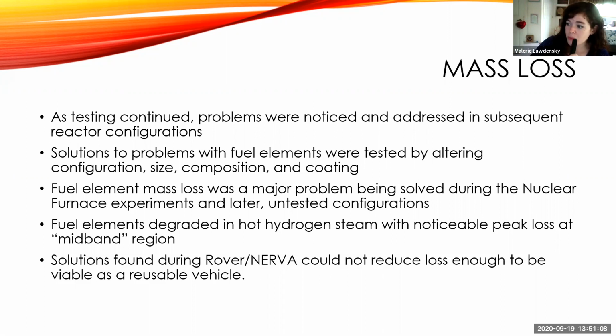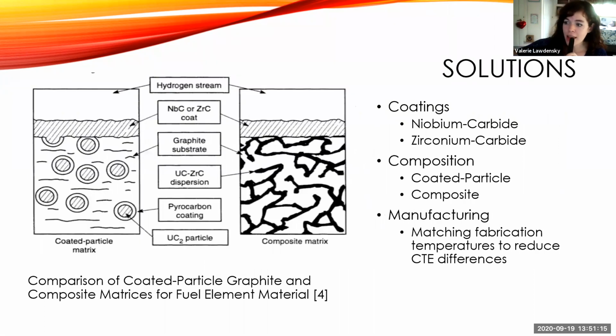So what they ended up doing was trying to experiment with options to try and fix it. The first one is they actually changed up the fuel element itself. Originally, they had taken the uranium particles and coated them in carbon, and then that was within a graphite solution. Then they did this composite matrix in which it's a little bit more distributed and they can get a little bit more of other things like the zirconium carbide, and that really helped. They also ultimately added these coatings.